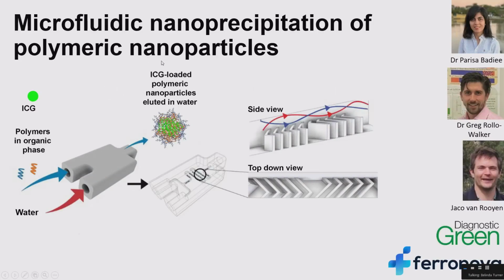So microfluidic, this is how we make these particles by microfluidic nanoprecipitation. We've got this nice 3D printed microfluidic device. We've got two inlets, one for the organic phase with the ICG dye and the polymers, and then one for water. So then these two inlets merge and then mix via this herringbone channel, and eluted in water is the ICG-loaded polymeric nanoparticles.